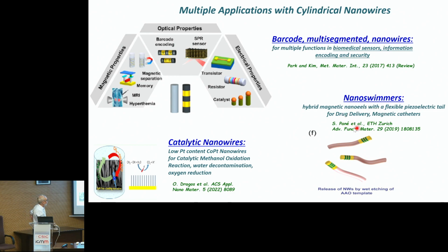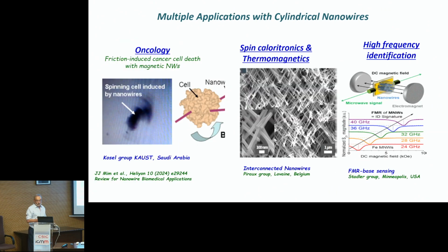Nanoswimmers: we are in contact with Salvador Pané in Zurich. They fabricate very nice hybrid wires with a magnetic head and a polymeric piezoelectric tail. So they have very interesting properties for drug delivery or magnetic catheters and so on. But also I see Puerto is very interested in the biomedical applications, so this is for you. There are some applications making use of these nanowires. In this case, the tumoral cell likes to eat the nanowire. Once the nanowire is inside the cell, you apply a low frequency magnetic field, and by friction, actually not hyperthermia, you can kill the cell.